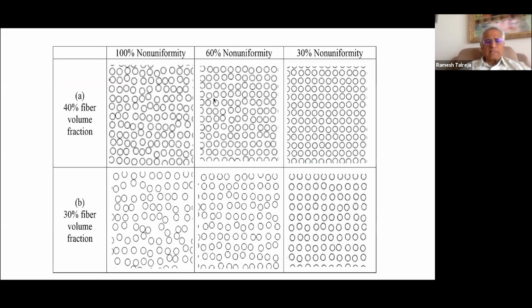Let me show you examples. Of course, it depends on the fiber volume fraction. That is, what's the initial distribution that you start out with. So let's say you start with 40% fiber volume fraction. With 100% non-uniformity, you look at a pattern like this. As you reduce the non-uniformity, it becomes more and more uniform. Obviously, at zero non-uniformity, you recover the uniform distribution. If there is more space between fibers, so it's 30% fiber volume fraction, you have a much more irregular pattern at 100% non-uniformity and so on.